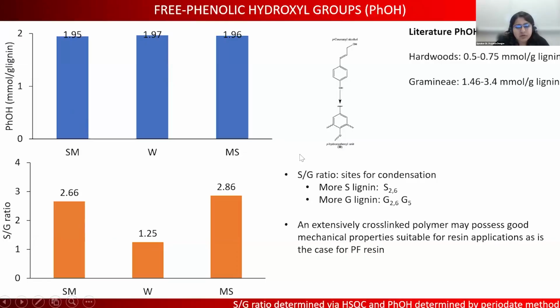The S/G ratio also is a key property of hardwood and grass lignin. The more S lignin would suggest that there are more sites for condensation at the S2 and S6 positions, whereas if there is more G present, then you'd have the G5 that would open up for condensation as well. And it was expected that if the polymer had more condensation sites, it would be more cross-linked and it would help with the mechanical properties, as is the case for PF resin, which is heavily cross-linked once it goes through its synthesis process.